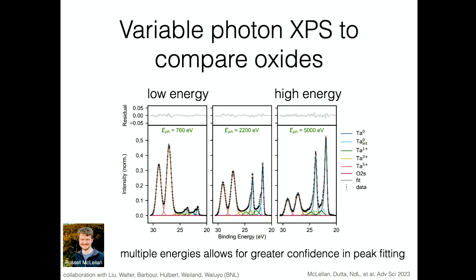So let me just say, full disclosure, I normally hate XPS as a materials characterization technique, because normally what you're doing is, this is the tantalum 4f spectrum, and I have these two peaks here and these two peaks here. These are the tantalum metal, these are tantalum oxide. And then I have this big mess down here. If you go into the XPS literature, people are making very strong claims based on a pedestal where they're putting in 2 peaks or 3 peaks or 4 peaks. And how do you know? How do I know that this is the right number of peaks? You're really just fitting a bunch of structure to something that has no structure. Okay, rant over.